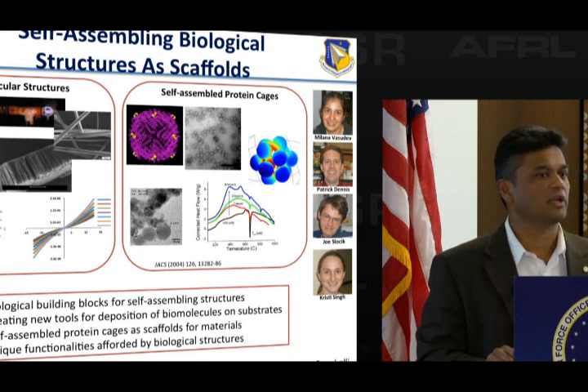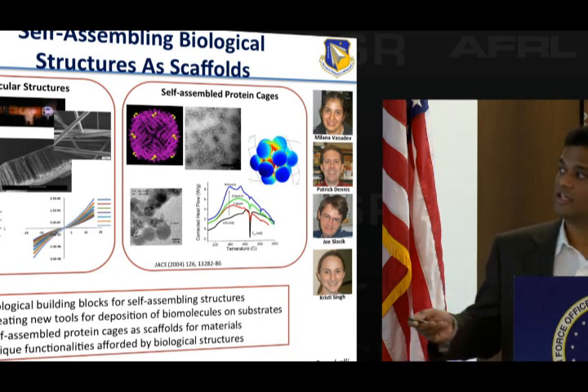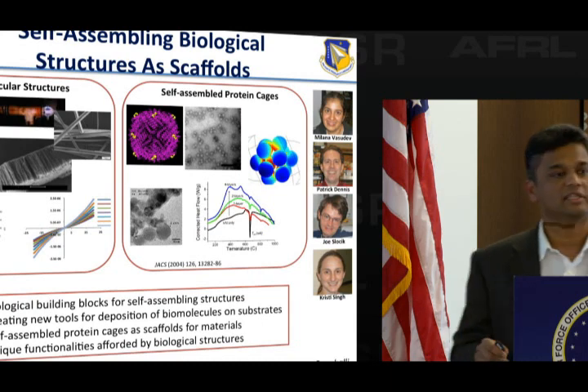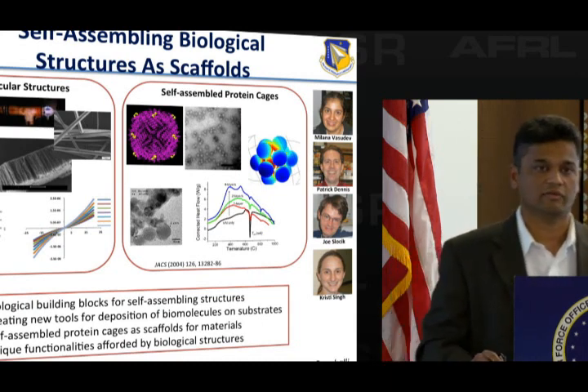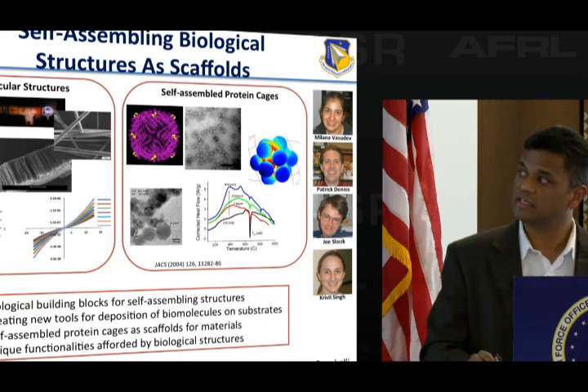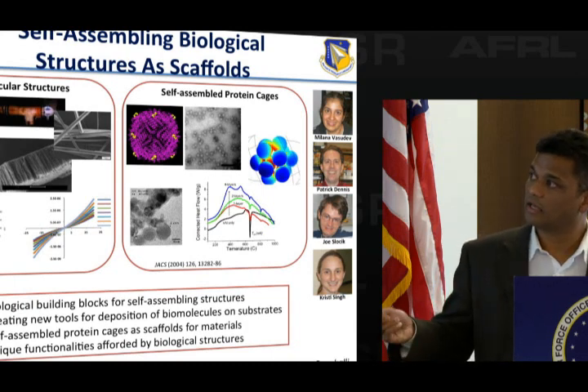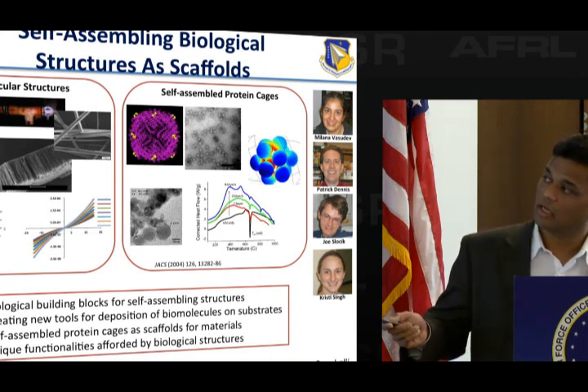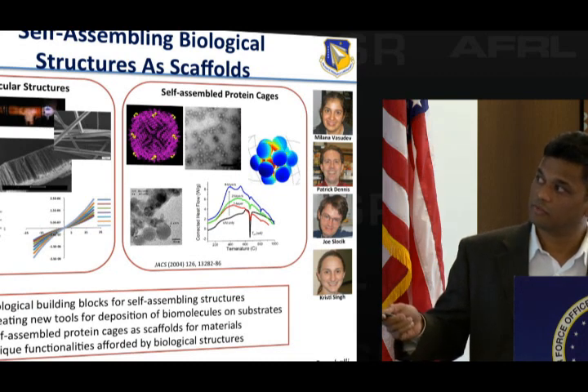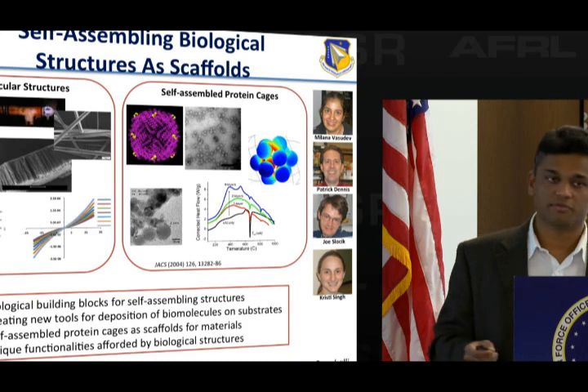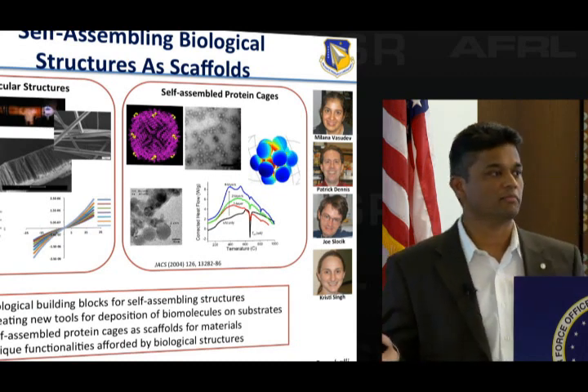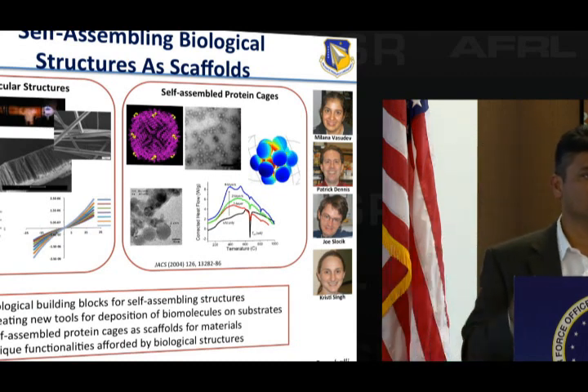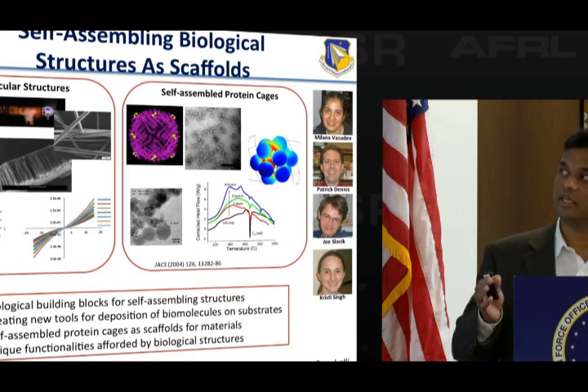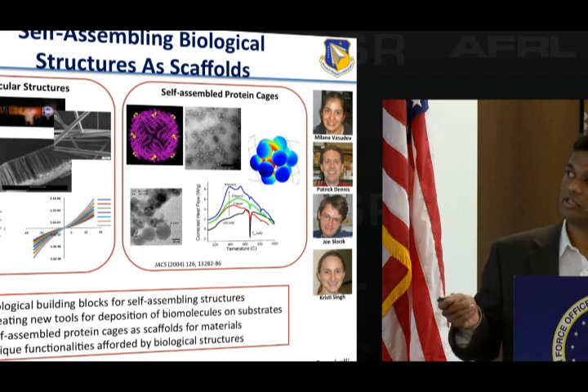So this is actually assembling protein cages on the surface of energetic particles and trying to see what happens to the energetics. Do we modify the energetics of nanoaluminum? And we've been seeing some very interesting properties arise from that. We also have some work in trying to use peptides to create supermolecular structures so we can create peptide nanotubes. So this is a forest of peptide nanotubes. Looks like carbon nanotubes, but this is completely made of peptides. So we're using diphenylalanine, so two amino acids, using a PECVD approach. This is in collaboration with Tim Bunning, and you can get very nice nanotubes formed.